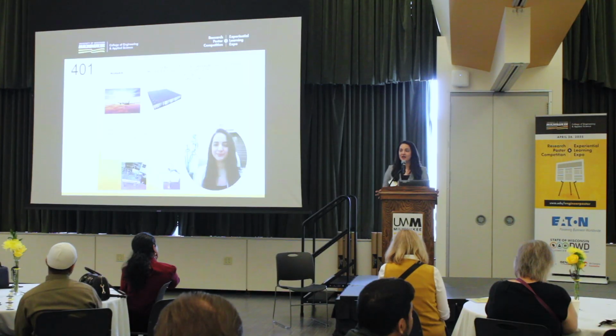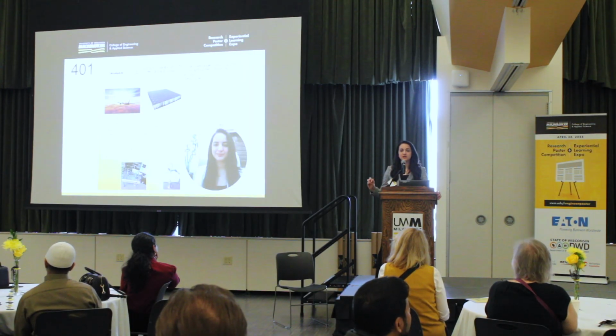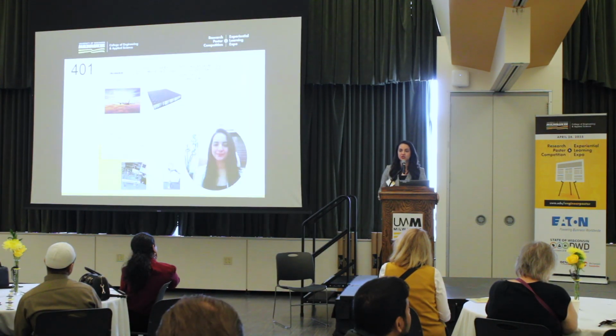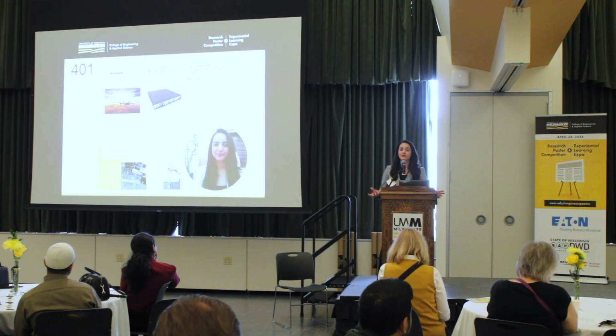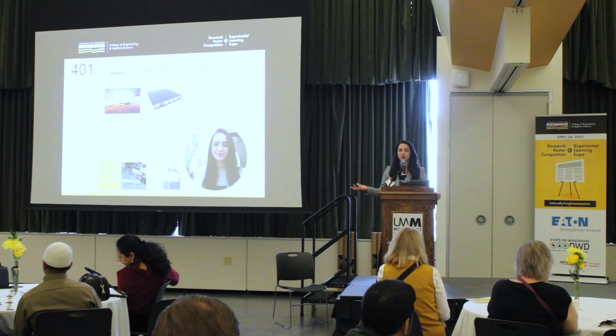To do that, I created different samples: intact samples, core spliced samples, impacted samples, and gapped samples. We applied a non-destructive technique called the impulse excitation technique, as mentioned, to lightly impact them and check their vibrational response. After that, we run them through the fast Fourier transform, FFT, to change these sound vibrations into frequency plots.